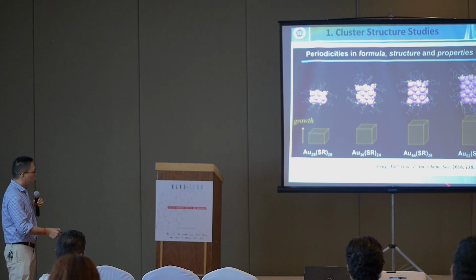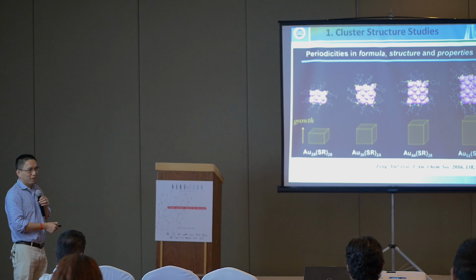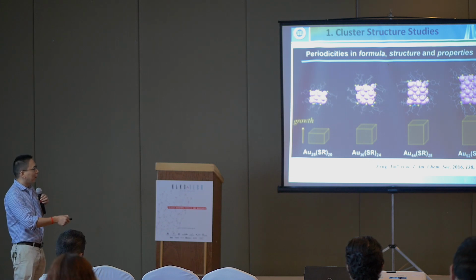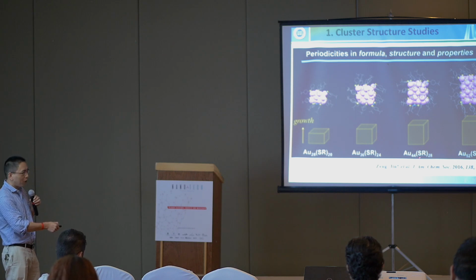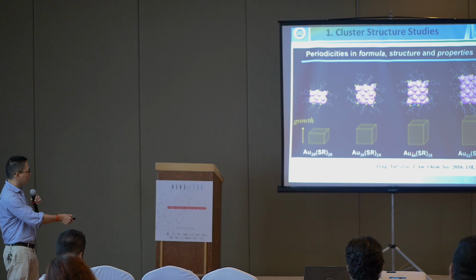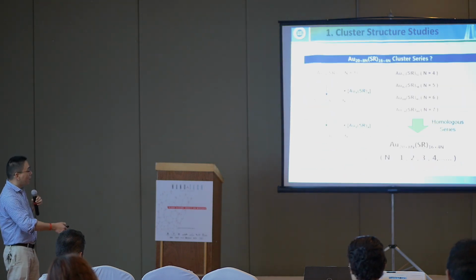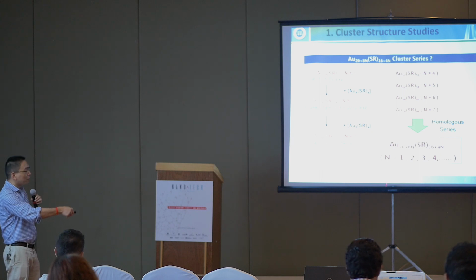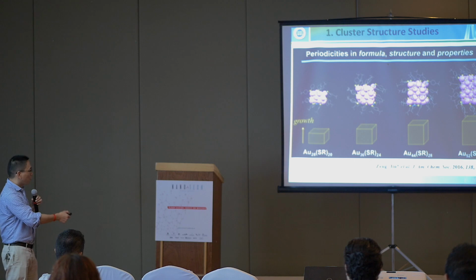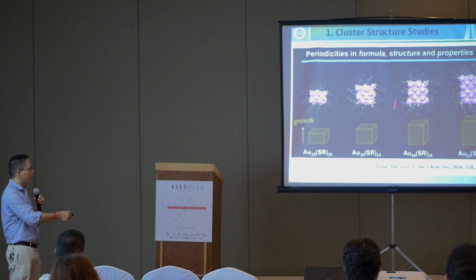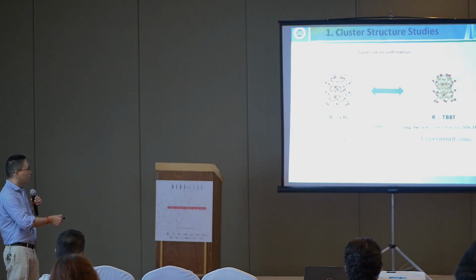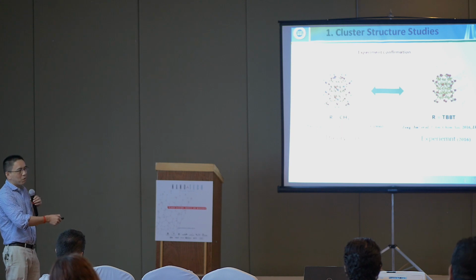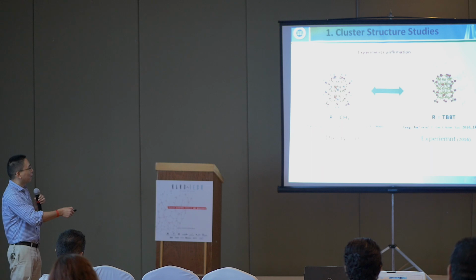So in 2016, Professor Jin successfully determined two cluster structures. This is Au44. This is Au52. Okay, and we can see here Au28, Au36, Au44, and Au52. This cluster series agrees with this evolution trend. And we have compared our selected models with the experimental ones, and we find our selected models agree very well with the experimental findings. We did not consider the ligand. We simplified the ligand to methyl groups.